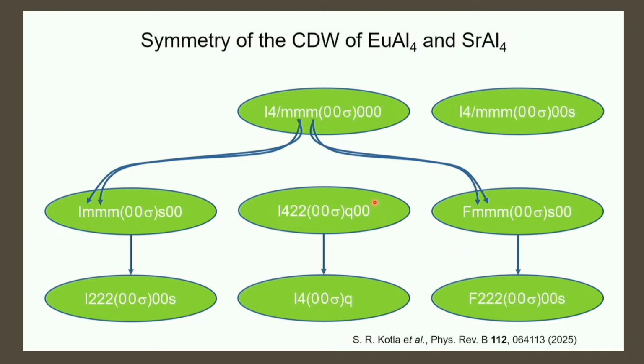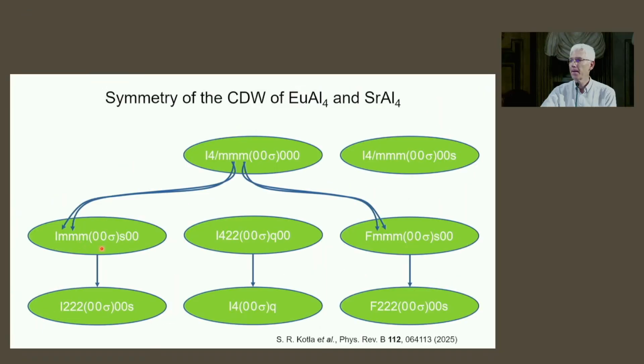Yeah, so this problem with I and F is that if we go from the I center and we keep these mirror planes and do away with the fourfold axis, we get Immm orthorhombic. And if we keep the other set of mirror planes, the diagonal mirror planes of I4/mmm, we get Fmmm. And here Immm and Fmmm orthorhombic are essentially different. As tetragonal, it's different settings, but as orthorhombic, it's different space groups.